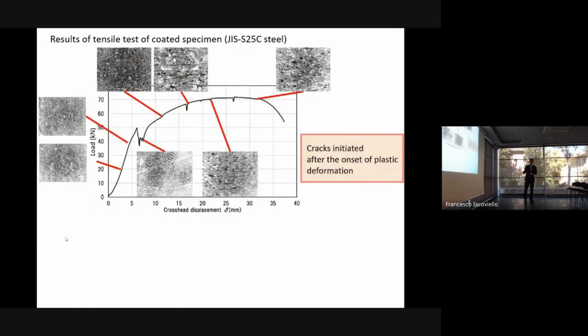Now, this is the result of the tensile test of coated specimens of carbon steel. This is the load and cross-head displacement with lateral surface morphologies. In the elastic region, there are no cracks, but cracks initiated after the onset of plastic deformation. A small number at first, but a large number then initiated and propagated.